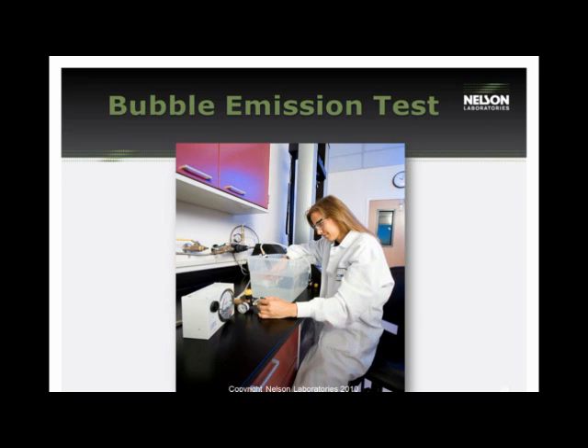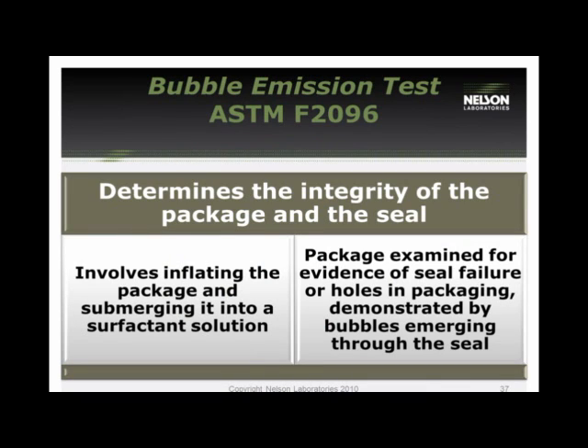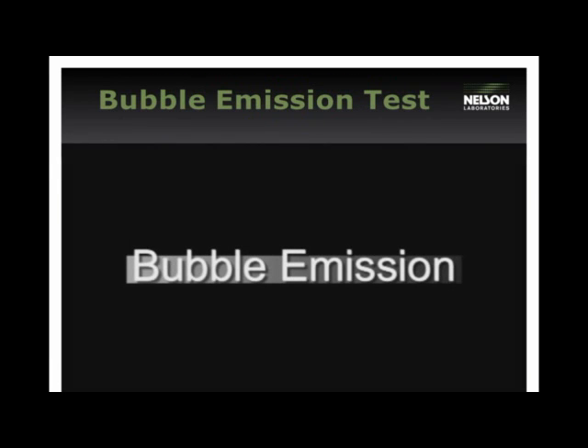The last option for integrity testing that we offer includes a bubble emission test. It is ASTM F2096. This will determine the integrity of the entire package and of the seal. This test involves inflating a package under a surfactant solution. Then you are looking for bubbles from a single location emerging through the seal. It's a whole package test versus what the dye migration evaluates, which is just a seal test.